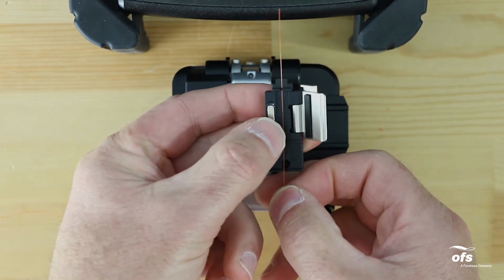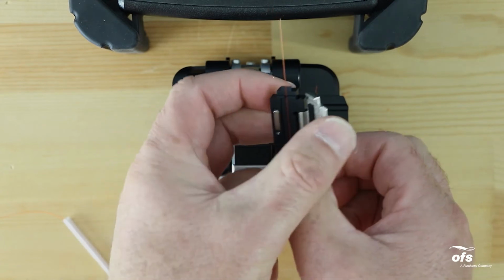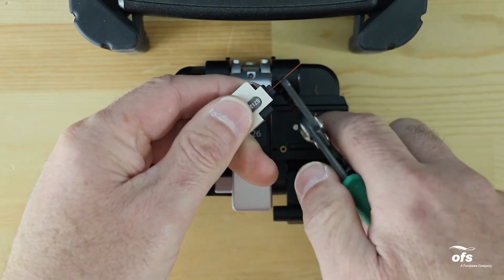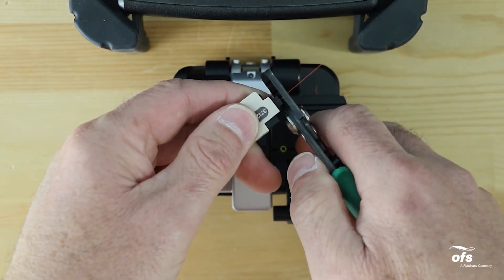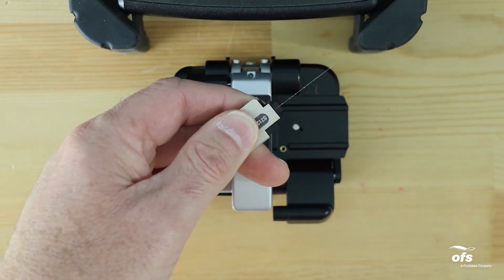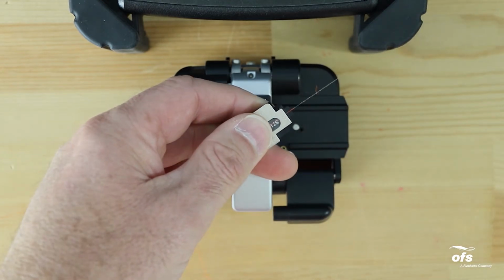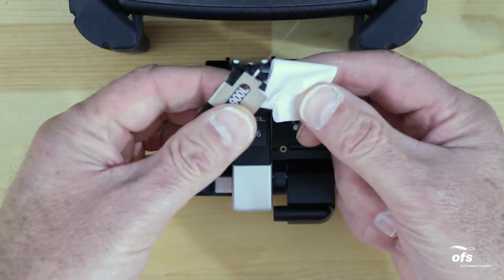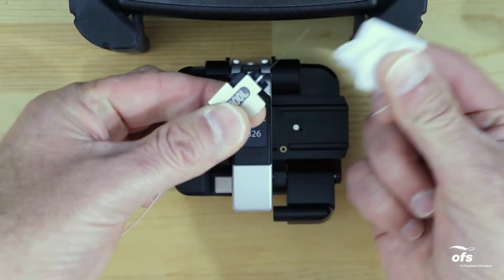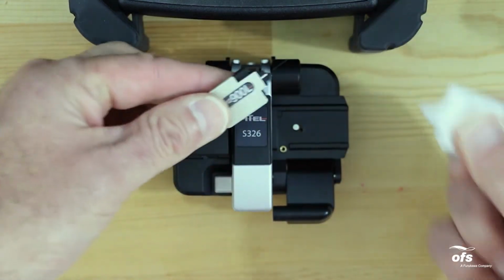You can also put fiber into the holder, leaving approximately 30 millimeters of 250 micron coating from the end of the removable holder, and strip the 250 micron coating from the fiber, leaving bare glass. Strip as close to the end of the fiber holder as possible. Wipe the bare fiber with a lint-free wipe soaked with fiber prep fluid.